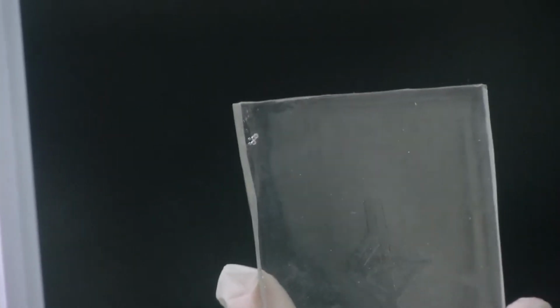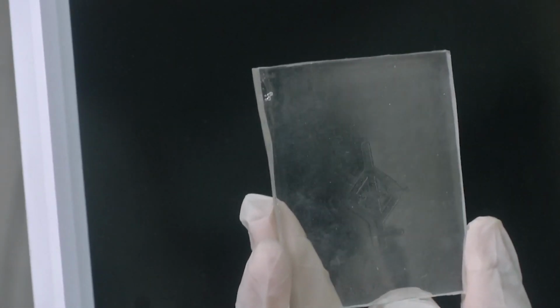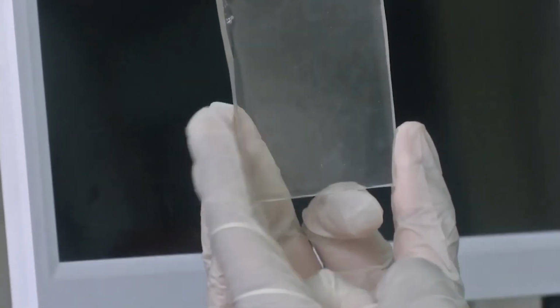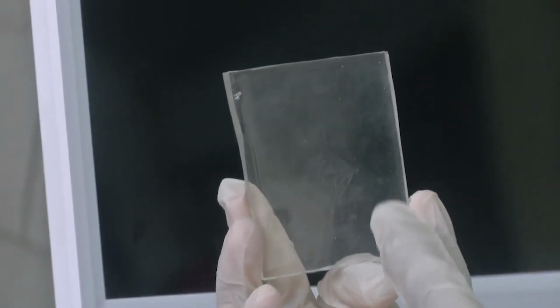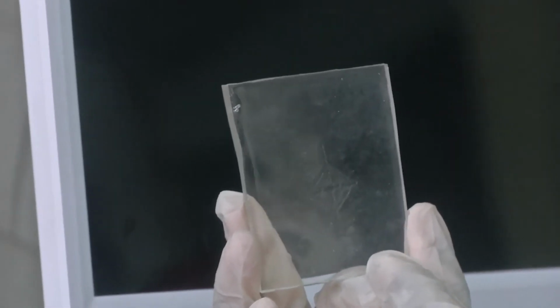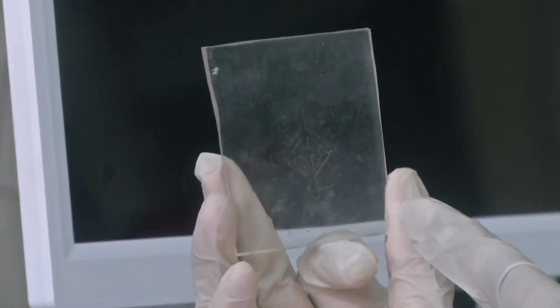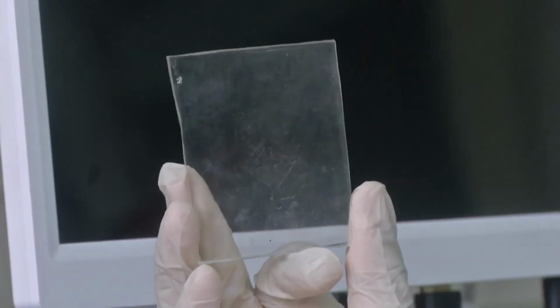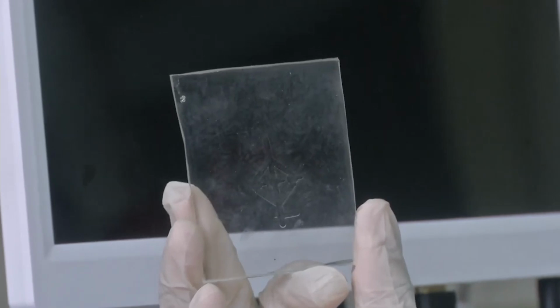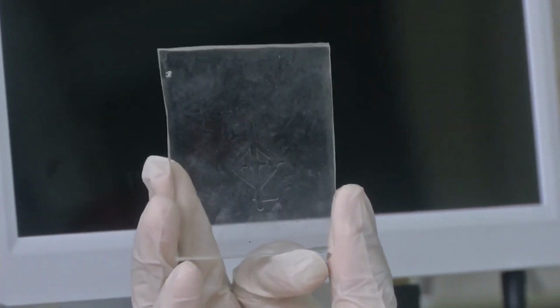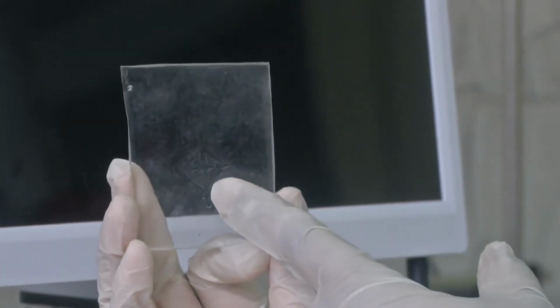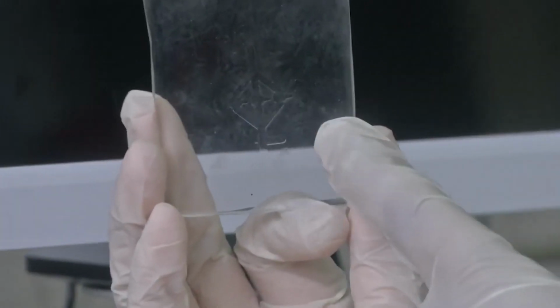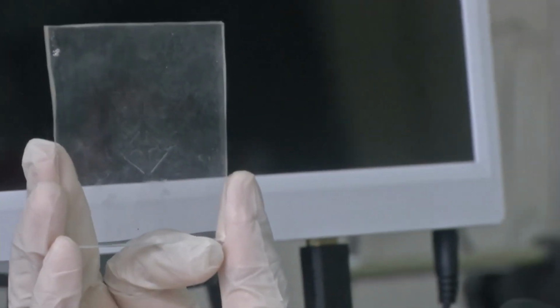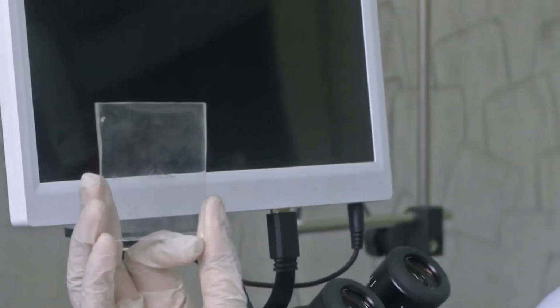So, always make sure you remove those bubbles. Here it is still okay to have the bubbles at the end because it is not hampering the device dimension. But when you do this sort of molding and then curing, a bubble tends to be retained inside the mold. If the bubble is somewhere in between your device structure, it could block your channels.